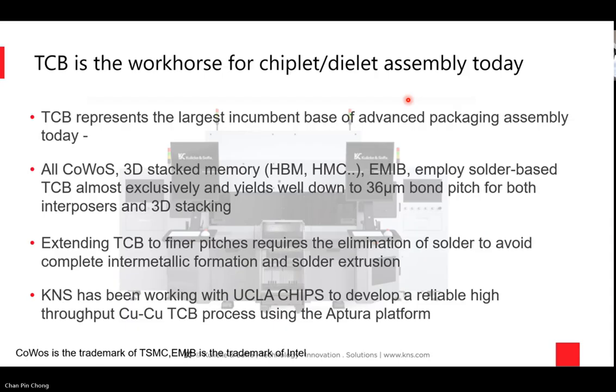Now, extending TCB to finer pitches requires the elimination of solder to avoid the complete intermetallic formation and the problem of solder extrusion, which leads to shorting and other reliability issues when you try to make the pitch shorter. So the key thing here is to see how we can eliminate solder and do copper-to-copper bonding. And we have been working, as I said, with KNS to develop a reliable, high throughput, copper-to-copper TCB process.